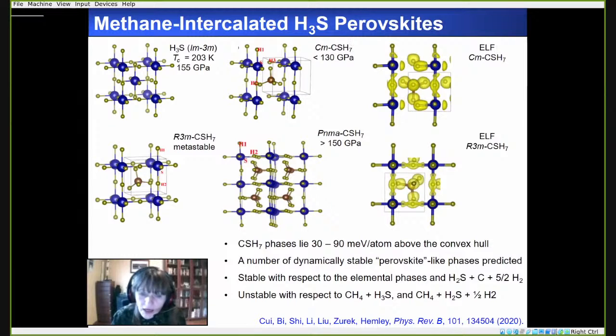It was not a thermodynamic minimum. It was always a metastable phase, meaning that it lay above the convex hull. This was stable with respect to the elemental phases. However, it was unstable with respect to methane plus H3S, as well as methane, H2S, and 1/2 H2. But it was dynamically stable. And I note that in these types of high pressure experiments, where you laser heat often to promote the formation of the species, it is not quite well known whether or not the species that you are going to be making is kinetically controlled or thermodynamically controlled.